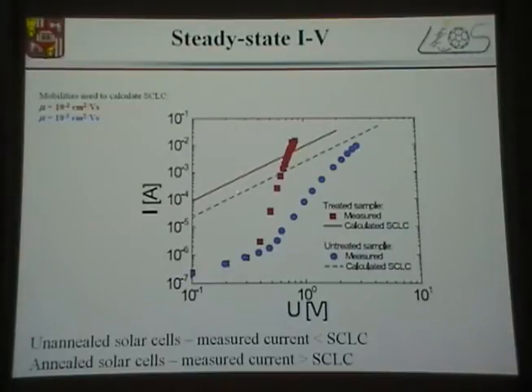And if you would try to compare them to the space charge limited current, which, to simple understanding, defines the top limit of the maximum current you can pump into the material, you can see that actually experimental data exceeds the space charge limited current. That's only possible when we have the double injection, so electrons and holes get injected, and the recombination is of non-Langevin type.